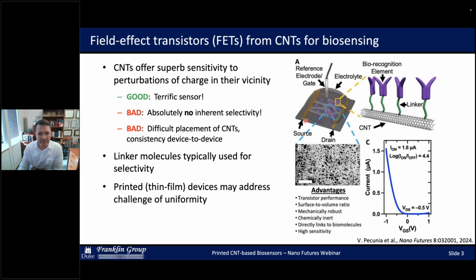And it's just to point out that there are many configurations, one of which would include some type of electrolytic environment for the gating medium, and then this linker type of structure that is either attached directly to the carbon nanotube film or perhaps through some intermediary like a non-fouling layer that's typically PEG-like in origin. And this allows for some biorecognition element to be attached and thereby modify or modulate the signal of the device in a way that indicates presence of a target species.